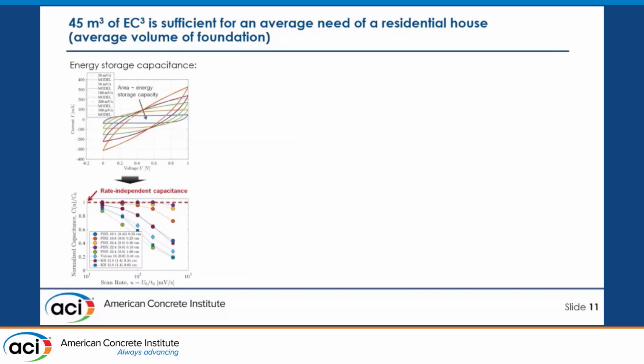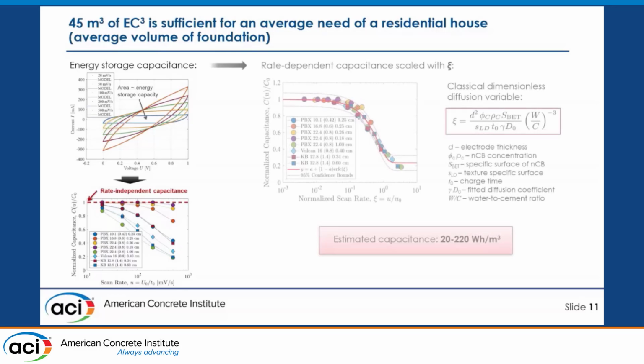An example can be KCl solution of different concentrations. When we want to quantify how much energy we can actually store, because this is the key point, we perform galvanostatic charge-discharge tests and cyclic voltammetry tests. Here I'm presenting just CV curves, where we applied a constant rate of voltage and monitored the current. While charging and discharging, we have those loops, hysteresis, and the area under these curves gives us information on how much energy we can store. Then we perform these tests at different scan rates, and we can reach the rate-independent capacitance. This is important since we want to obtain values which are invariant with laboratory conditions.